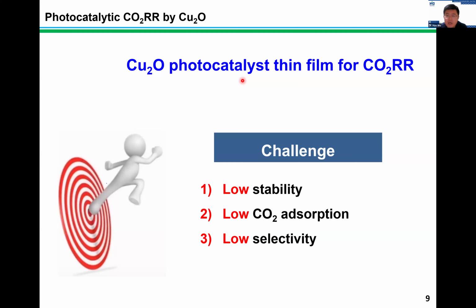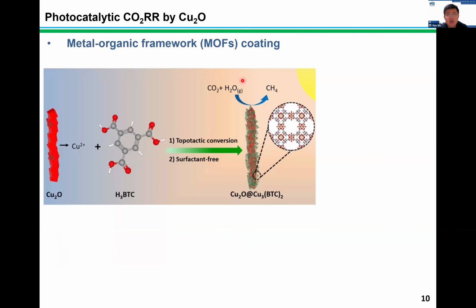However, compared to other products, the carbon dioxide to methane conversion requires 8 electrons of charge transfer, which is kinetically more demanding. So in this situation, our group wanted to come up with one strategy that can simultaneously address these three challenges together. After a thorough investigation, we decided to coat a copper-based metal organic framework on the surface of cuprous oxide using the topotactic conversion strategy, which is relatively new.